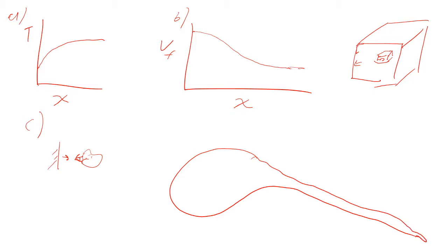Right, and up here is the situation that was just described. So you have very large compressive surface forces. And back here, this is thin enough that it cooled uniformly, right? So this is still very fragile and very thin. Up here, you've got a big blob, right? And you can basically take this and whap on it with a hammer, the front part, and nothing will happen, right?